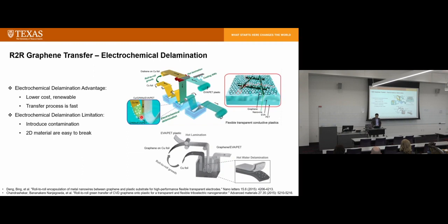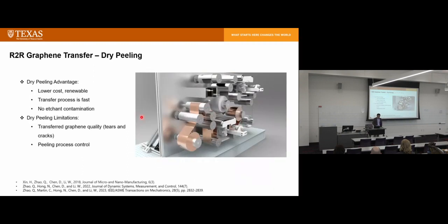So what we are doing, we're trying to develop a method that is dry. We also want to do large-scale graphene transfer, so it's a roll-to-roll process, but we don't want to introduce any chemicals. So in the process, we're trying to use a graphene dry transfer process. So we laminate our top cover, transparent substrate, onto graphene on copper. We mount it on our machine, and then we can delaminate using a peeling method. So this is a purely mechanical peeling method.